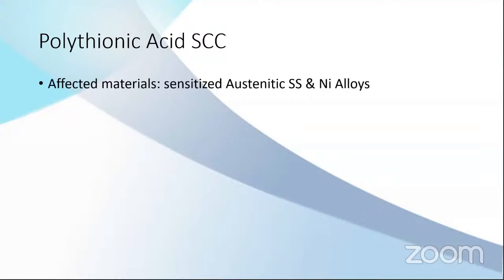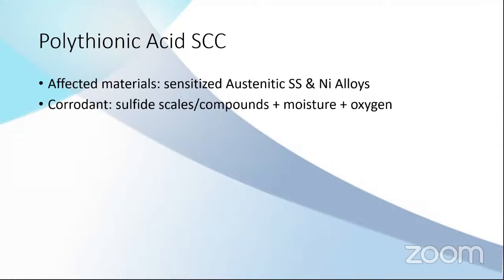This polythionic acid stress corrosion cracking is caused by sensitized stainless steel and nickel alloys. So it's still related to the previous damage mechanism, but with the corrodant, if it's sensitization, you get faster corrosion, but not cracking. But if you have the corrodant in the form of sulfides, moisture, and oxygen, then it may cause cracking.